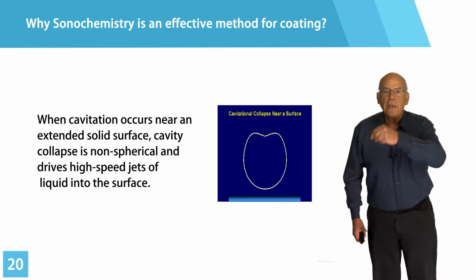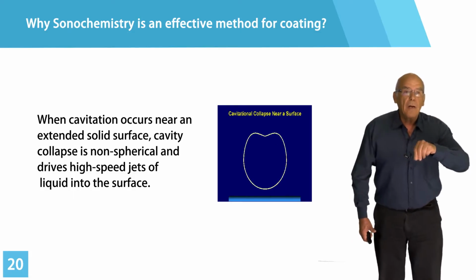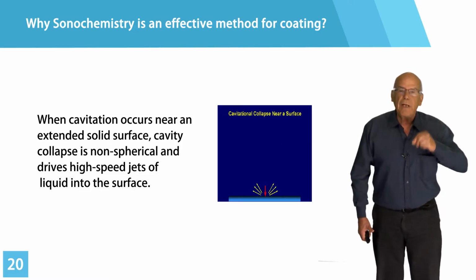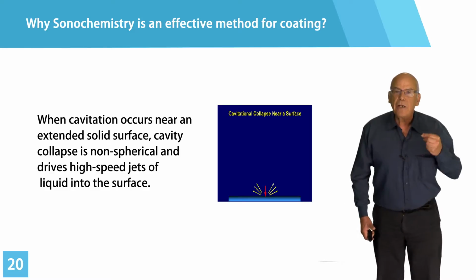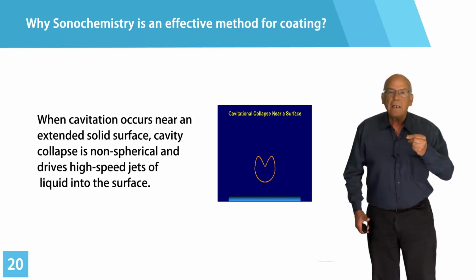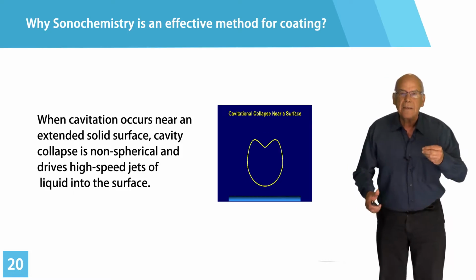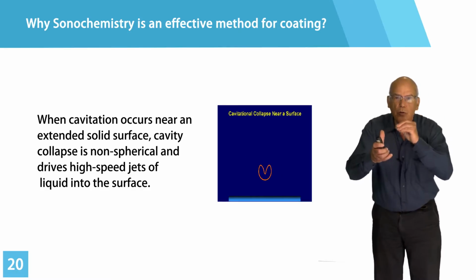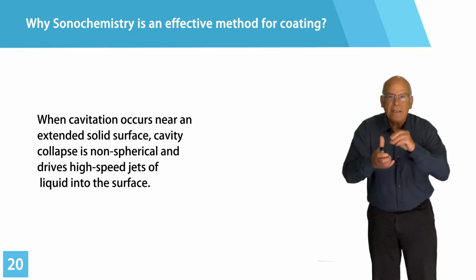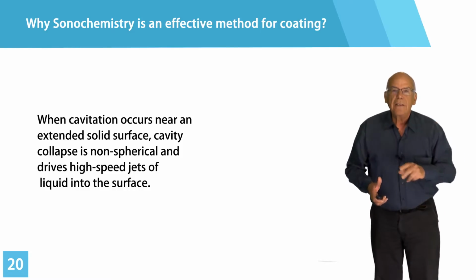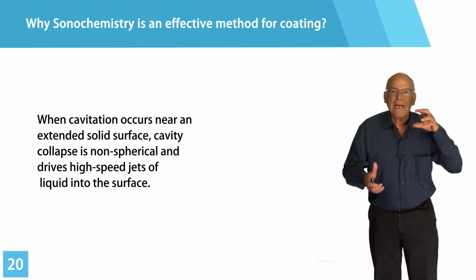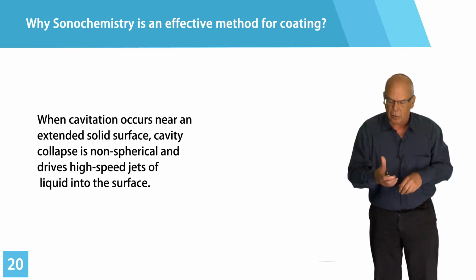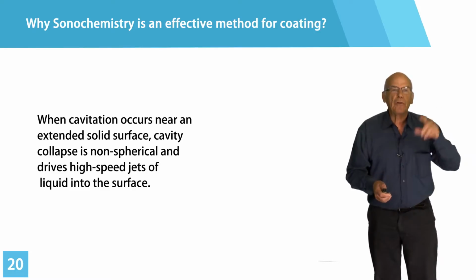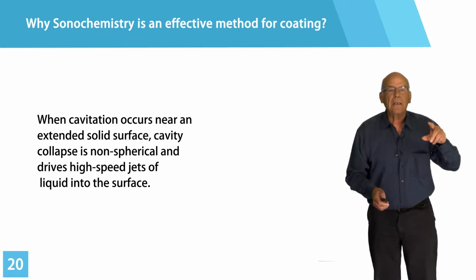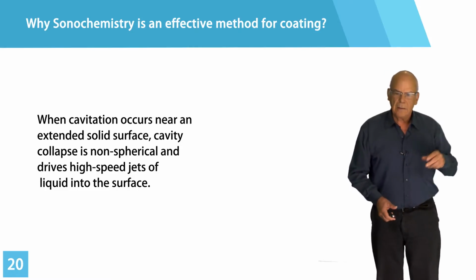These are all solid surfaces. When the bubble collapses near a solid surface, there is an after effect. And this after effect is involved with some microjets that are moving very fast. And they are taking nanoparticles, throwing them directly onto the solid surface, embedding them in the surface in such a way that it's very difficult to remove them. They are staying there well embedded in the solid surface. So this is a deposition, a coating technique that in certain cases is unparalleled. There is nothing near it.